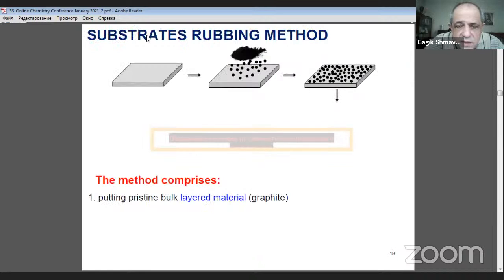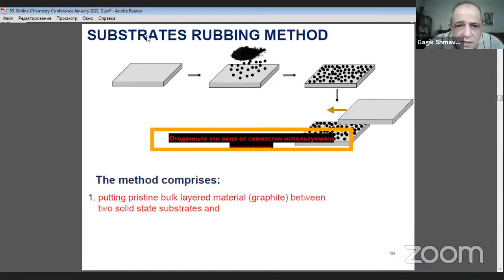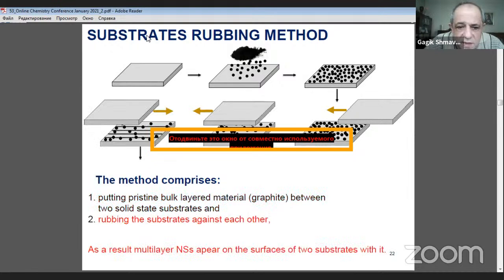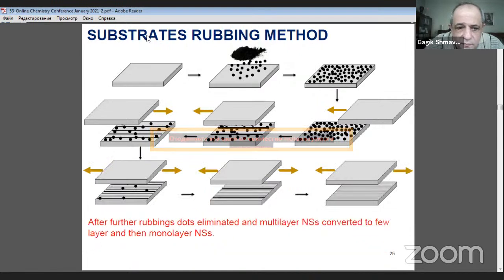So here you can see the rubbing process. The method comprises putting pristine bulk layered material such as graphite between two solid substrates and rubbing the substrates against each other. As a result, multi-layer nanosheets appear on the surfaces of the two substrates. After further rubbing, dots are eliminated and multi-layer nanosheets are converted to few layer and then monolayer nanosheets.